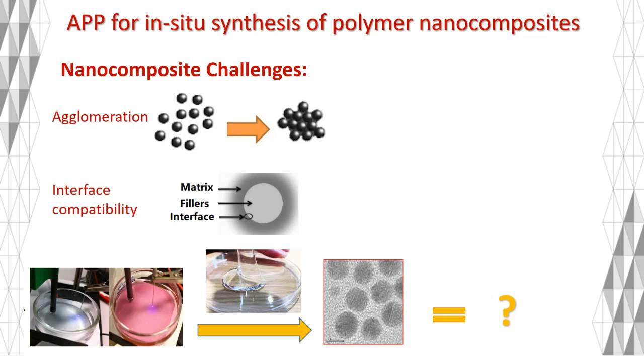The production of polymer composites poses several challenges, including achieving effective dispersion of nanoparticles and also ensuring good compatibility at the nanoparticle and matrix interface. Most hydrogel-based nanocomposites have been created through sequential mixing of pre-synthesized nanoparticles with hydrogels. However, this approach often results in nanoparticle agglomeration and inhomogeneous distribution.